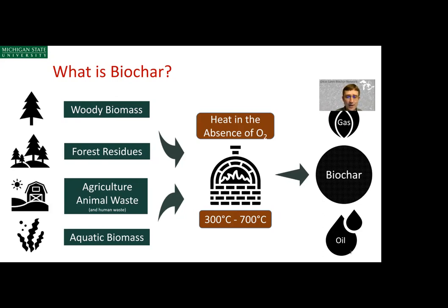From there, we heat those biomass forms in the absence of oxygen, and this is very important. If we let in too much oxygen, we'll combust all of the biomass to CO2 and water vapor, and we won't get very much biochar or bio-oil if the liquid is what we desire. The temperature range we are most interested in typically occurs between 300 and 700 degrees Celsius, perhaps an even more narrow range of 400 to 600 degrees Celsius is even more typical.